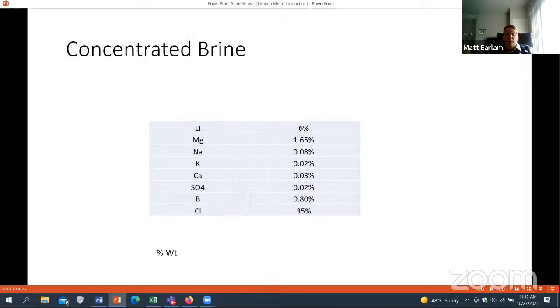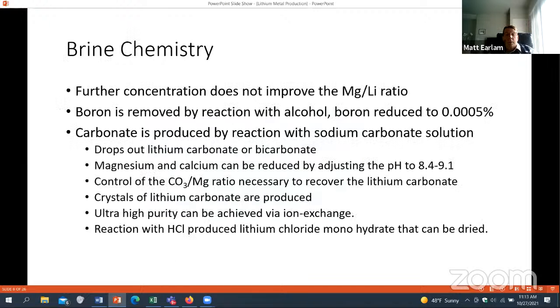So you look at the concentrated brines, we can get to situations where we're pretty high in lithium, 6%, and then magnesium and sodium, potassium follow along. Sulfates are minimized, and then we still have a significant fraction of boron that we're going to have to deal with. So further concentration by evaporation doesn't improve the magnesium to lithium ratio. Basically we have to do a carbonate addition to get the lithium separated from the magnesium.